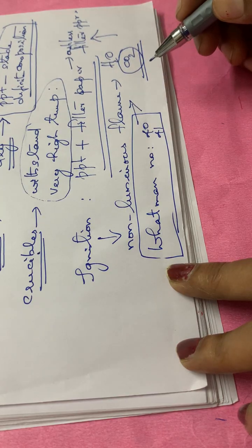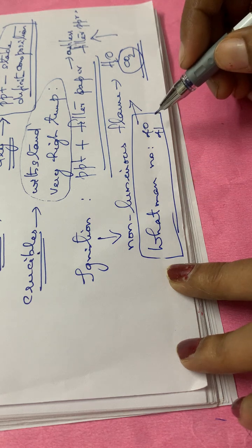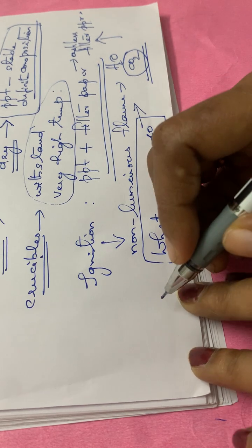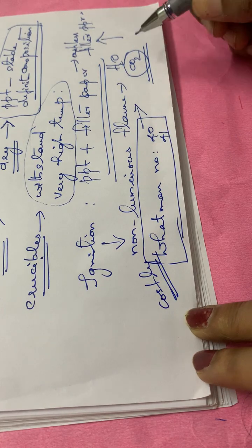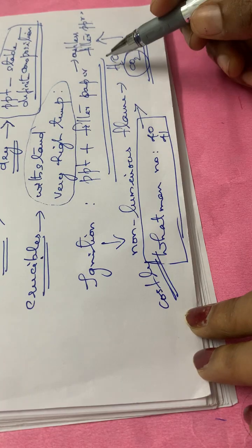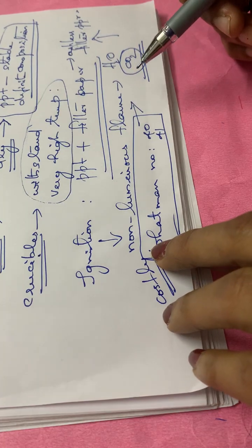We are not at all using a normal filter paper or a normal paper. We are using a Whatman number 40 or 41 filter paper, and it is quite costly also. The peculiarity is that it is an ashless filter paper. So we are igniting the precipitate along with the filter paper, and after a particular temperature, or after 15 or 20 minutes, the filter paper will be burnt off and there will not be any ashes remaining in that particular crucible.